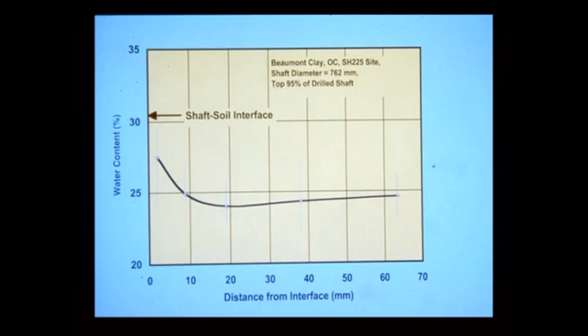In a clay, this effect produces an additional decrease in shear strength, and it may produce swelling. These data are from samples cast against the face of a drill shaft in stiff Beaumont clay in situ. This is not a lab test, but an in situ test, and it demonstrates clearly the effect, where you have a higher water content immediately adjacent to the face of the concrete wall. The water-cement ratio, by the way, in this particular case, that was used to maintain concrete fluidity was 0.60, and we would hope that you would not use such high water-cement ratios now.